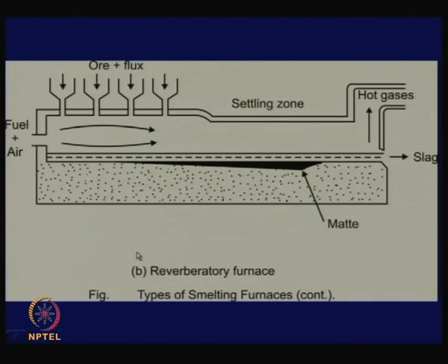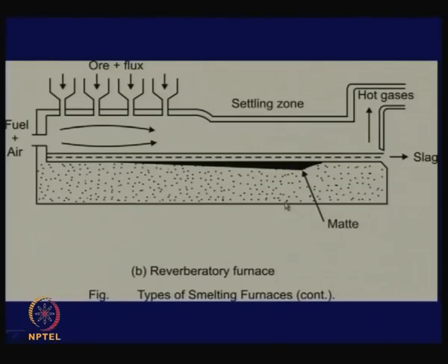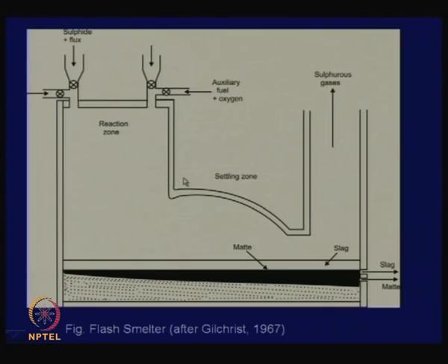We have smelting in the case of sulphide ores also, but sulphides do not give metal straight away. What they give is a phase called matte, and we have an operation called smelting, where the sulphides are first partly roasted and then the whole charge is reduced. There is a slag phase, and we do have a separation of slag from the metallic values, but the metallic values stay basically as a mixture of sulphides. In the case of copper, iron sulphide and copper sulphide, we call that matte. So, there is matte slag separation. So, smelting can be of two kinds, metal slag separation or matte slag separation. This I will discuss in detail when we come to extraction of copper.